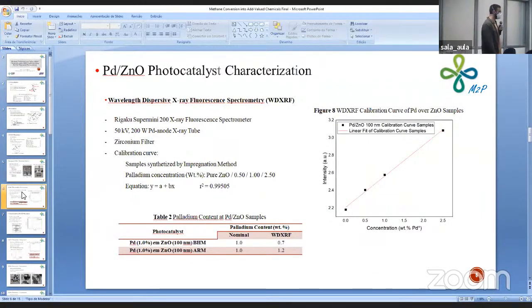As characterization techniques, we first have the wavelength dispersive X-ray fluorescence spectrometry. We carried out this technique in order to determine the composition of the synthesized materials and the palladium content in the samples. Given the low content of metal in the samples, we built a calibration curve that is presented in figure 8. And in table 2, we have the obtained results of the palladium content in the samples, and they are close to the nominal, confirming the presence of palladium in the samples.